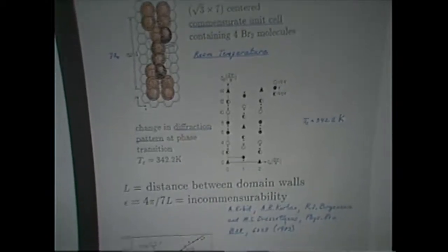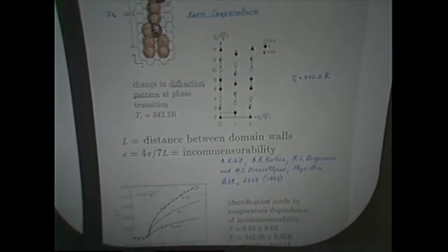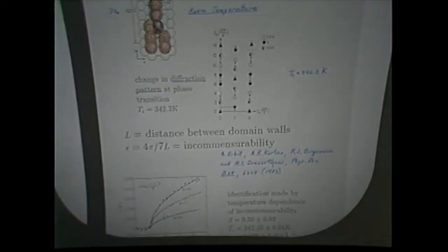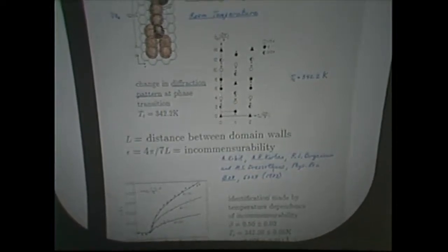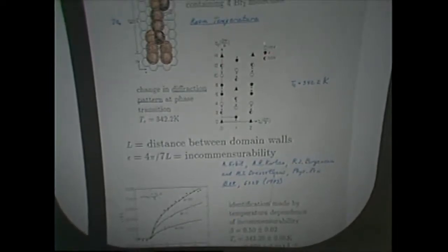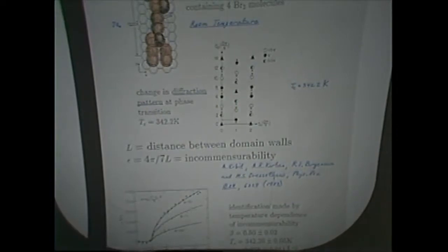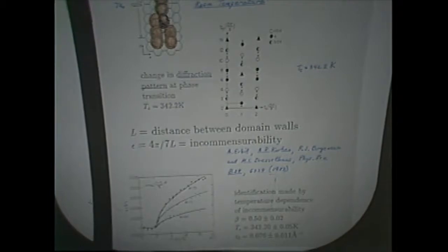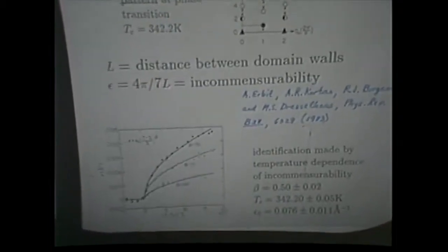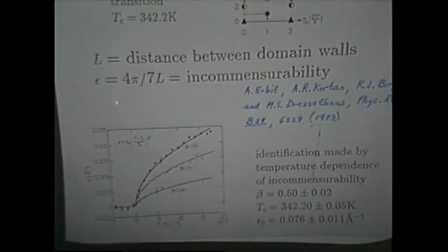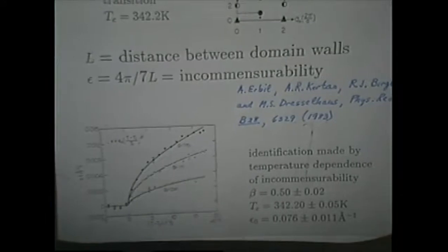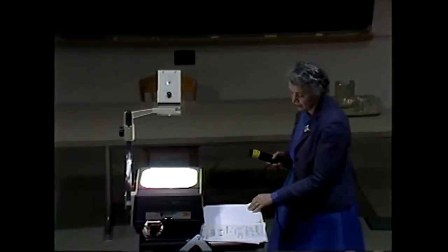But after we go above this temperature, 342 degrees, where we started seeing this Gaussian line shape in the Raman spectrum, these spots no longer are divisible by this distance, but they move in the direction of the arrows, firstly by little amounts, but always in this ratio given by this code. Now, the fact that they move in this prescribed manner and the incommensurability, which is related to the reciprocal of the domain size, the fact that this incommensurability has a unique temperature dependence, which depends on the reduced temperature to the 1/2 power, this and the motion of the spots are an indication or a signature for the onset of the stripe domain phase.